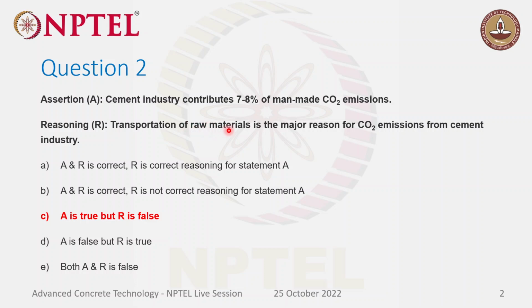The major reason is, so we all know that calcium carbonate is one of the major raw materials in cement production. If you take 1 ton, about 60 to 70% of the raw material will be limestone, right? So to produce 1 ton of Portland cement, about 1 ton of carbon dioxide will be released. Okay. So calcining the raw material is one of the major reasons for carbon dioxide emission. Transportation also contributes, but it is not one of the major reasons for carbon dioxide emission.